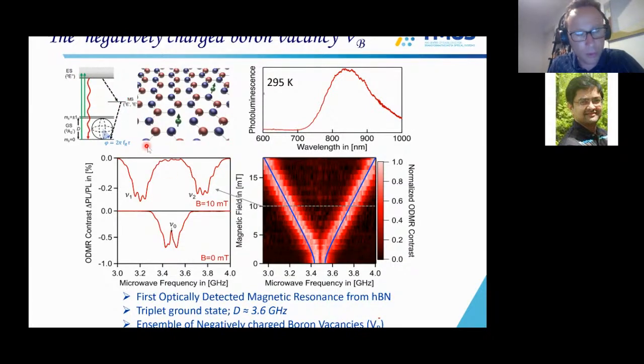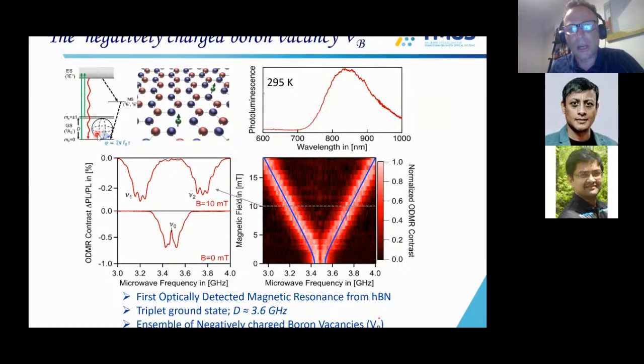Fluorescence lifetime is a bit short; it's around 1 nanosecond. And one of the most fascinating things about this particular defect is we still don't really know where the zero phonon line is. You can actually cool it down to 4 Kelvin, and there is no zero phonon line appearing. So the zero phonon line transition is actually dark, which is unusual for color centers.